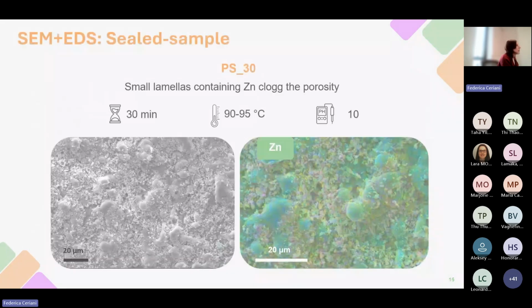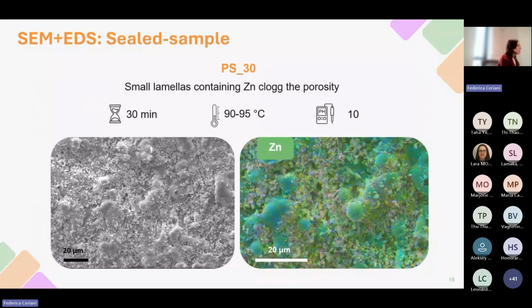Now let's introduce the first sealed sample, let's say the reference one, that is named PS30. This sample is produced by immersing the PEO-coated specimen into the nitrite-containing solution for 30 minutes. The solution is heated to 90-95 Celsius degree, and its pH is equal to 10.